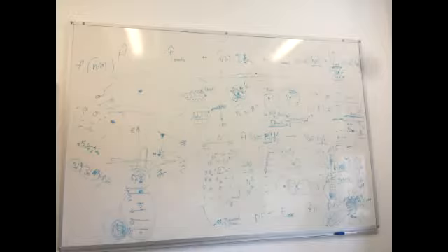The solution of this equation gives you the density, but you see that the equation itself contains density. So it's interrelated, and doing it once you cannot get the right answer. So you have to loop it. You take some initial guess. To calculate these terms in this equation, I will guess some initial n. Let's say I take a non-interacting system, as if I just put my non-interacting atoms there, and assume this is my initial density.